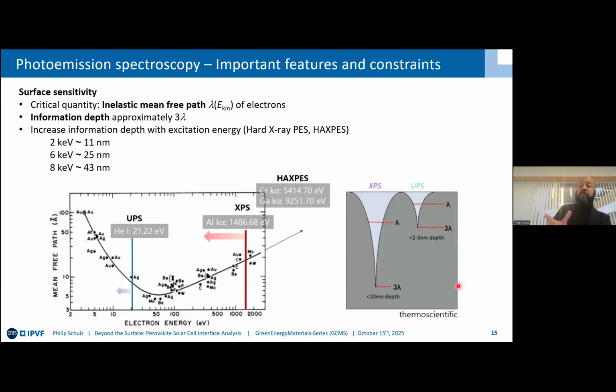First, of course, some general points about HAXPES or photoemission spectroscopy. I talked about the surface sensitivity already a lot qualitatively, but quantitatively, the critical quantity is the inelastic mean free path. When you look into this view graph here, this is something that has been recorded in the 80s and 90s, the so-called universal curve of inelastic mean free path of electrons in matter. And it shows that with a factor of 2 or 3, you have more or less the same attenuation, irrespective of the element that the electron needs to traverse. And you see a very distinct dependence on the electron energy.